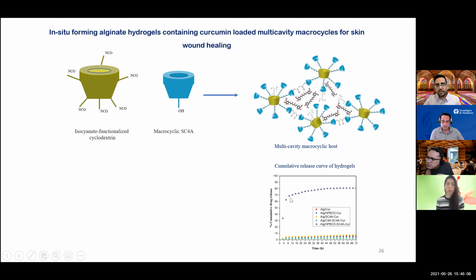And as you can see here, the best result is for this multi-cavity macrocyclic host. After 72 hours, we have approximately 80% release of curcumin, and it's really good, because we know that curcumin has a hydrophobic structure, and we always have some problems regarding the bioavailability of this material and regarding its release. The other hydrogels, as you can see here, have less than 10% release.